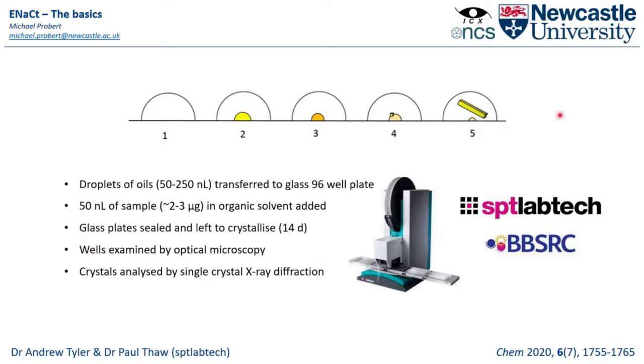And then we nominally seal the whole system with an extra glass plate on the top, which allows us to examine all of the conditions by optical microscopy, and it allows any extraction of our sample to be done and analysed by single crystal X-ray diffraction. So that was our cartoon mock-up.